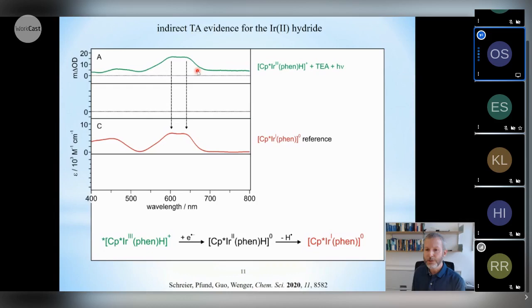We get quite a nice transient UV-Vis absorption spectrum, which, however, corresponds rather convincingly to the UV-Vis spectrum that we can measure for this isolable reference compound. It is the iridium(I) compound that I mentioned previously, lacking a ligand. And so what we think is occurring here is a rapid reaction sequence as displayed at the bottom.